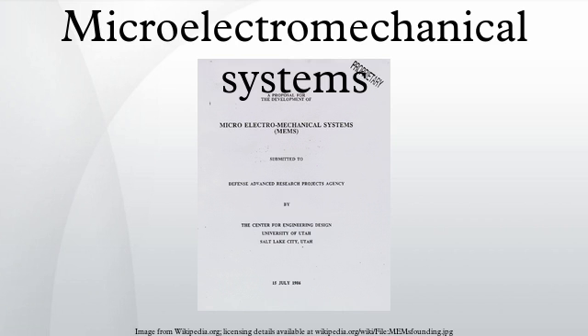In the first variation, the etch cycle is as follows: SF6 isotropic etch; C4F8 passivation; SF6 anisotropic etch for floor cleaning. In the second variation, steps 1 and 3 are combined. Both variations operate similarly. The C4F8 creates a polymer on the surface of the substrate, and the second gas composition, SF6 and O2, etches the substrate.